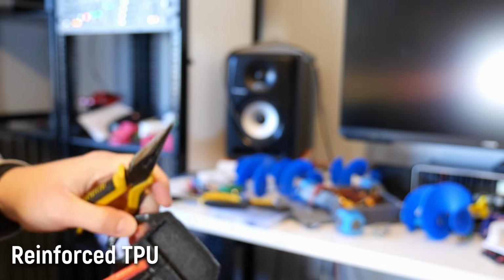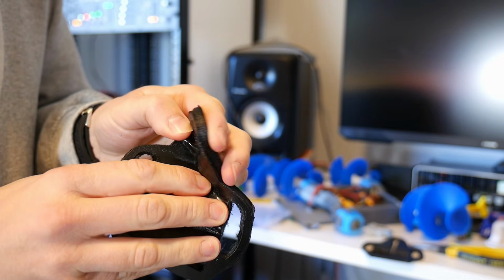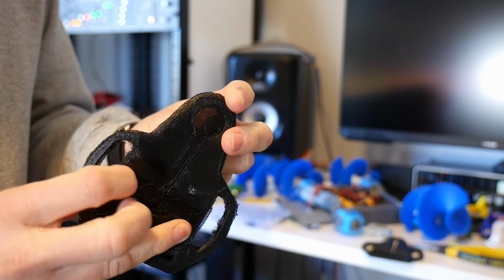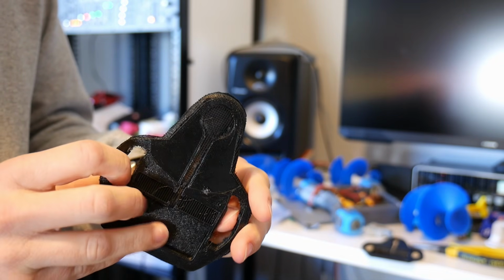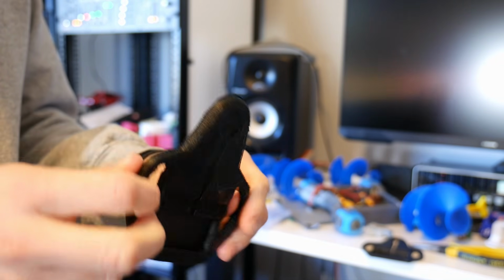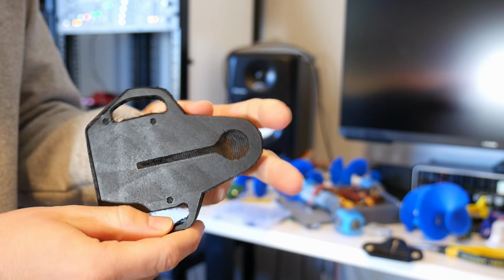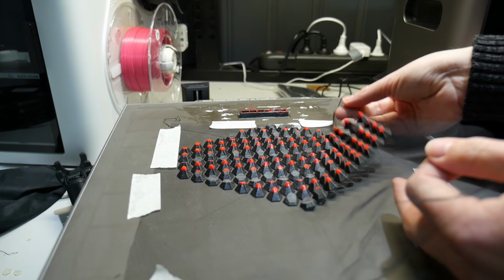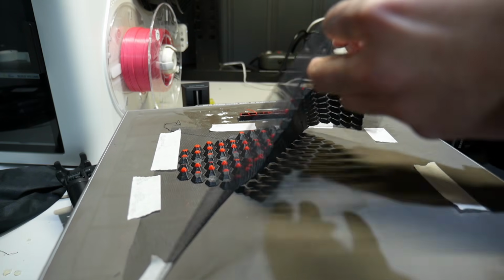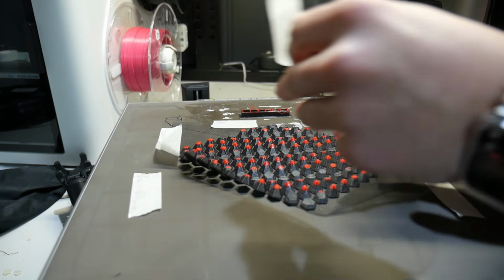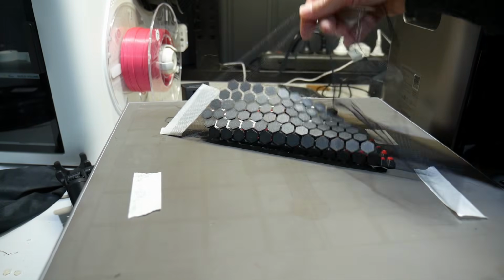When it comes to these materials, I think most of their resilience actually comes from the fact that they can deform and spread the load out, but when it's fused in place like this, it's only really thin nylon strands that can easily break when they're locked into the matrix of the plastic. I'm not giving up on that idea yet, but it does need more experimentation. However, should you try 3D printing on fabric? Yes, absolutely. It's a ton of fun, but I would say only really do it for aesthetic reasons unless you figure out a better way to incorporate the stronger mesh.